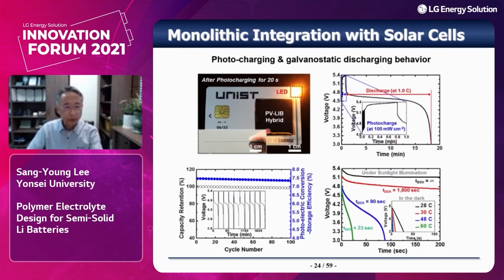So please take a look at this photo. Our hybrid cell, composed of a solar cell and a solid-state cell, was inserted into a credit card. Please take a look at the cross-sectional view. We can expect from this result that our hybrid cell is very slim in terms of thickness. After exposure to sunlight for 20 seconds, we can successfully operate the LED lamp for longer than 20 minutes.